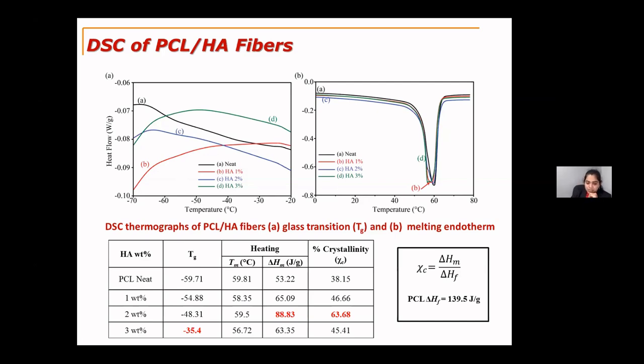So we chose to check the enthalpy from the melting endotherm here. From the melting endotherm, I calculated the crystallinity of the fibers. The crystallinity is calculated from the enthalpy of the melting endotherm relative to the fusion enthalpy of the neat PCL. The crystallinity of the neat PCL fiber was around 38, but with the nanoparticles, it moved up to 46, 63, and 45. So infusing the nanoparticles definitely improved the crystallinity of the fibers.